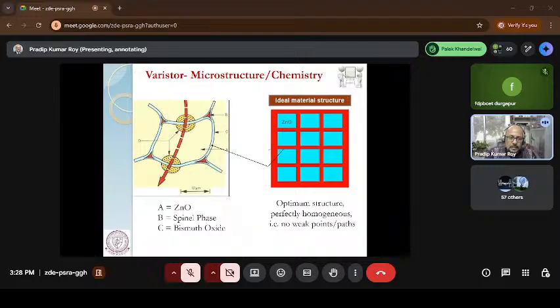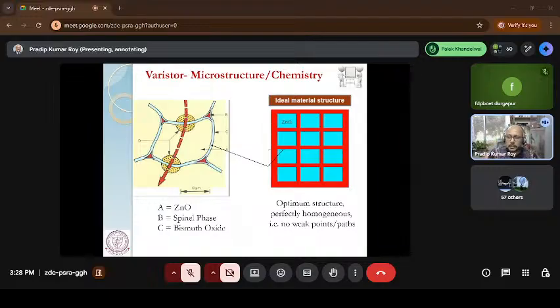Ideally, this zinc oxide is the blue color, and the bismuth oxide is the red color. Ideally, all zinc oxide should be coated with bismuth oxide. Now, zinc oxide is a semiconductor, whereas bismuth oxide is an insulator. So in the normal operating condition, as I said, it acts as an insulator. When the current passes through, because bismuth is an insulator, the current cannot pass through the zinc oxide. Zinc oxide is a semiconductor, any current can pass through it. But because it is coated with the bismuth oxide, it's very difficult to pass the current through that bismuth oxide layer. So you have to break that bismuth oxide layer, and only then will it pass through.